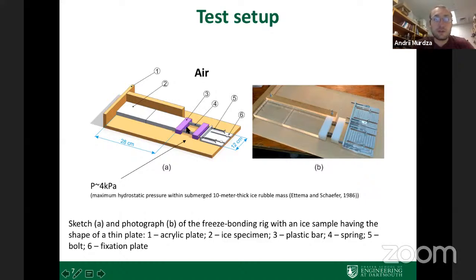Then we added some compression using this mechanism, as you can see, with two plastic bars and springs. We could vary the pressure, but for all the tests we used a pressure of 4 kilopascals, which is the maximum hydrostatic pressure within a submerged 10-meter thick ice rubble mass. The whole setup, the orange part, was made from acrylic because it has a low heat conductivity. We wanted to ensure that all the heat flux occurs perpendicular to the bond, along the long axis of the sample. One important thing to mention is that these experiments were done in air, not submerged in water. On the right, you can see an image of how it was done.